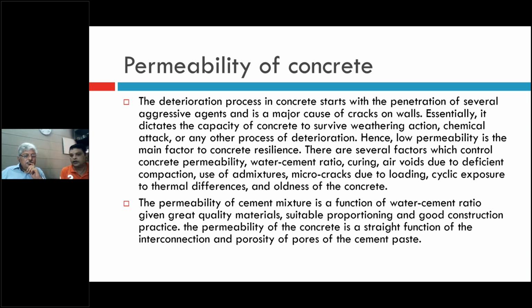All the weathering action, all the chemical reactions start to take place immediately, because when cement is in contact with water, a chemical reaction takes place, and every chemical reaction evolves heat, and that heat has to be quenched by putting on water. When it is put in lesser quantity, cracks will still occur, though in lesser water the cracks will be less. The water cement ratio should be maintained. And even if it is for longer periods, that is also not good. So it has to be done under proper supervision.